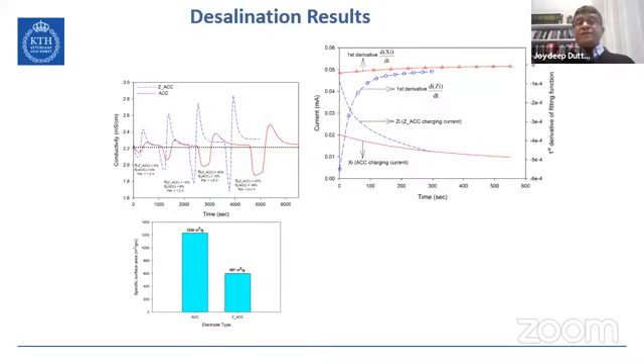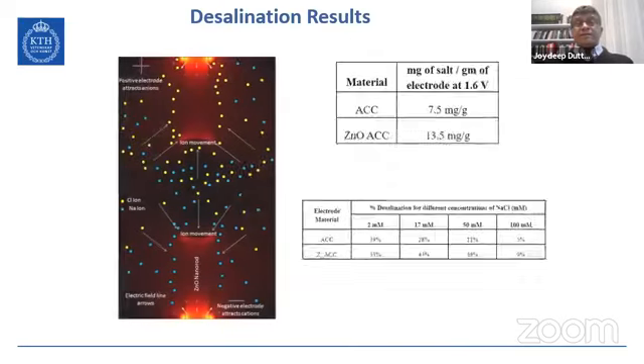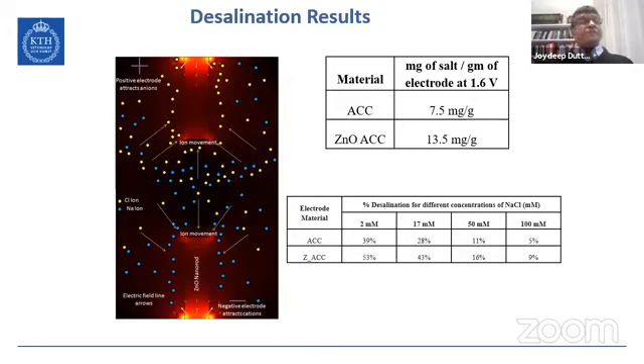So these are some more results. I will just skip it and give you the most optimized values that we were getting. It's about 13.5 milligram per gram that we are able to remove with the zinc oxide nanorods.